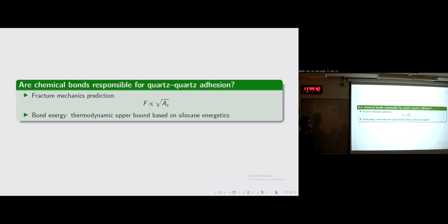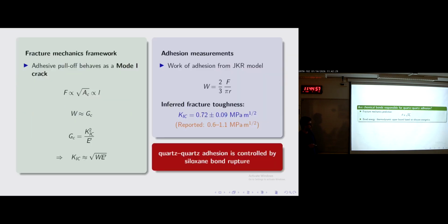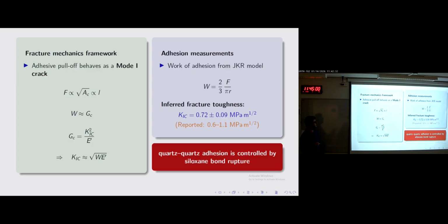I need to convince you that chemical bonds are responsible for this adhesion that we see. I'm going to approach this through fracture mechanics prediction, and then also do an energetics calculation from bond energy. The reason I'm going to fracture mechanics is really because of the scaling that we see from the blue data set, where the adhesion force scales in general with the square root of the contact area. That means it scales with a length scale. And if the projected area of the contact is circular, it would scale with the radius of the circle.